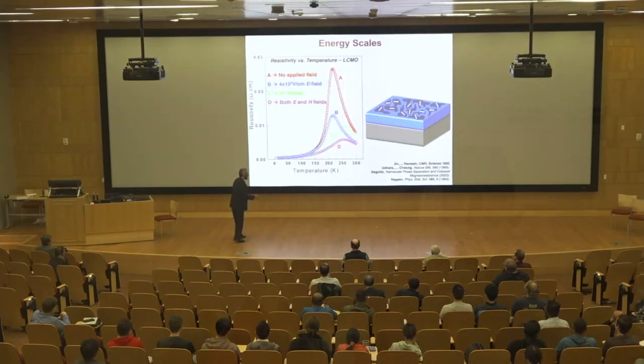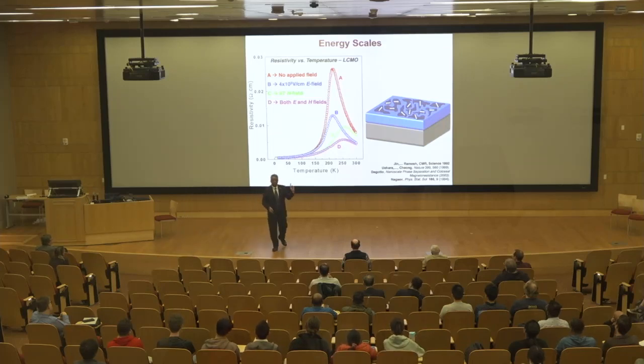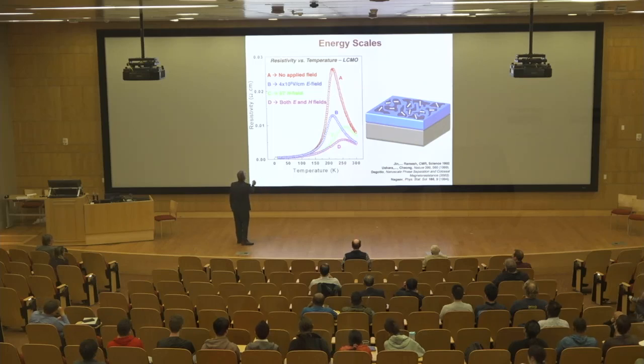All right, so energy scales. Now, one of the questions to ask is, okay, what's the deal with this energy scale? This is a simple slide, but it actually is kind of illuminating. This is data from way in the past. This is the so-called colossal magnetoresistance effect, which is something that we discovered back in the 1990s. You have a material which has a resistive transition like this, apply a magnetic field of 6 Tesla, you go from the red to the green. You apply an electric field of 400 kilovolts per centimeter, you go from the red to the blue.